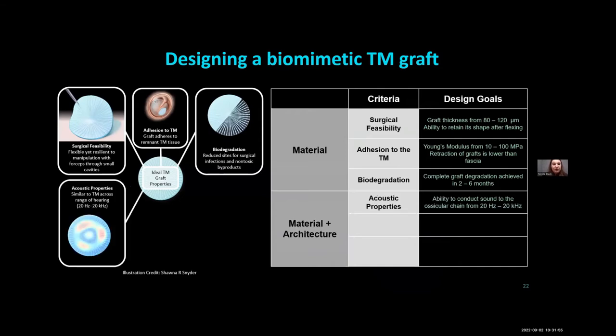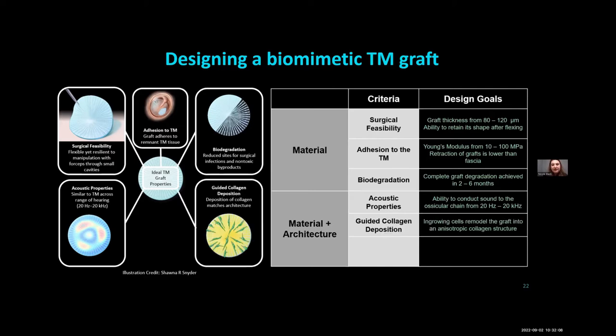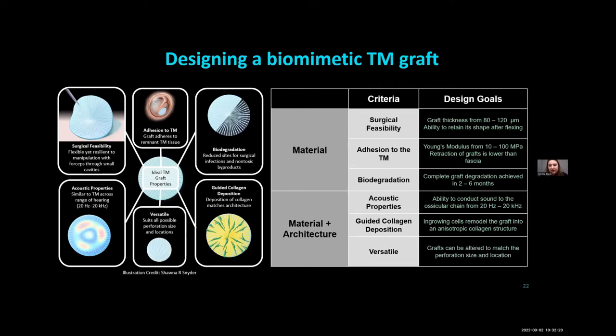We also aimed for good acoustic properties of these eardrums, being able to vibrate across the wide range of frequencies that you and I can normally hear, generally considered to be about 20 hertz on the lower end up to 20 kilohertz on the higher end. And not just vibrate at these frequencies, but over time, as this graft degrades, be able to guide tissue so that it would match this architecture and be replaced by tissue in this architecture over time.